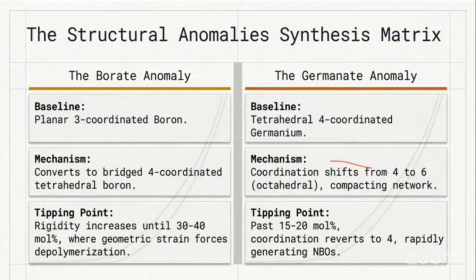What happens here is, initially the trigonal borate groups bridge together to form the tetrahedral borate structures. Whereas in germanate, the coordination shifts from tetrahedral to octahedral, which leads to formation of a much more compact network beyond 33 mole percent. The network which was converting from trigonal into tetrahedral boron suddenly depolymerizes to form once again the trigonal borate groups. That is where it starts forming an anomalous behavior, which leads to generation of non-bridging oxygens inside the network.